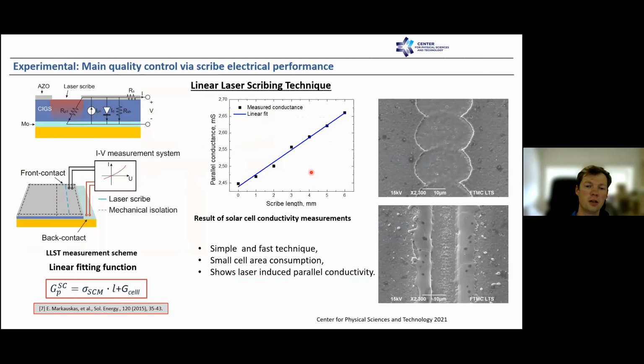We also developed a technique where we can optimize our laser processes. We call this the linear laser scribing technique. Basically, we can measure the additional parallel conductance of a laser scribe caused by material degradation due to exposure to the laser. So what we do is scribe some predetermined scribe length, and then measure the IV curve. From this scribe and measure procedure, we can extract specific parallel conductance values of a laser scribe in Siemens per meter units. This is a really good way to characterize our laser process, so we have to keep these parallel resistances as low as possible.